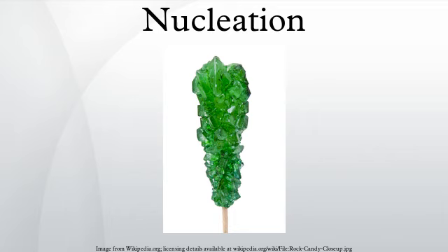The model assumes that nucleation occurs due to impurity particles in the liquid tin droplets, and it makes the simplifying assumption that all impurity particles produce nucleation at the same rate. It also assumes that these particles are Poisson distributed among the liquid tin droplets. The fit values are that the nucleation rate due to a single impurity particle is 0.02 per second, and the average number of impurity particles per droplet is 1.2. Note that about 30% of the tin droplets never freeze. The data plateaus at a fraction of about 0.3.